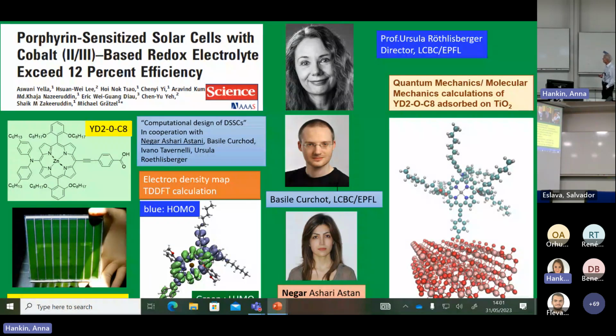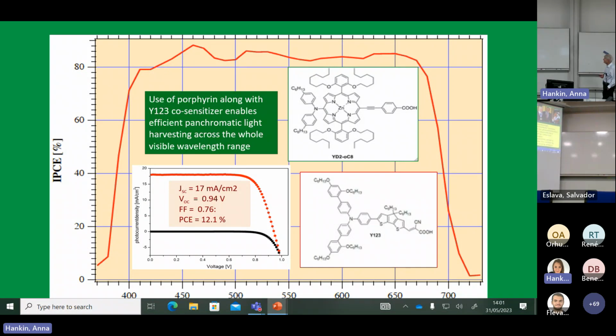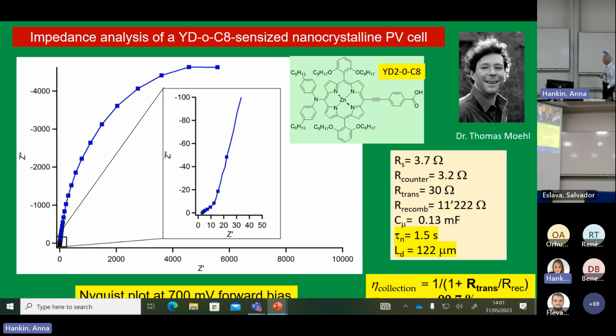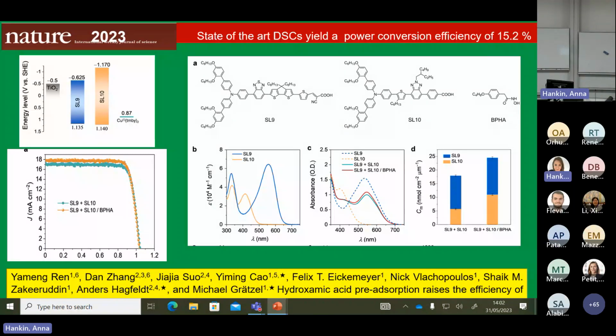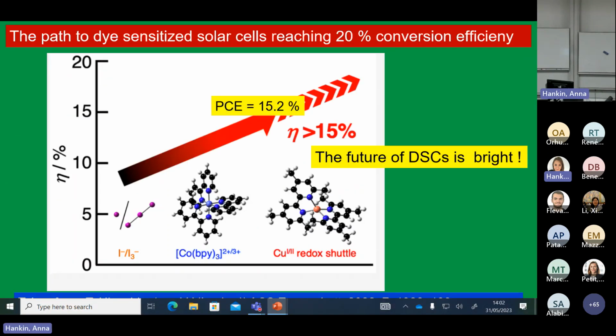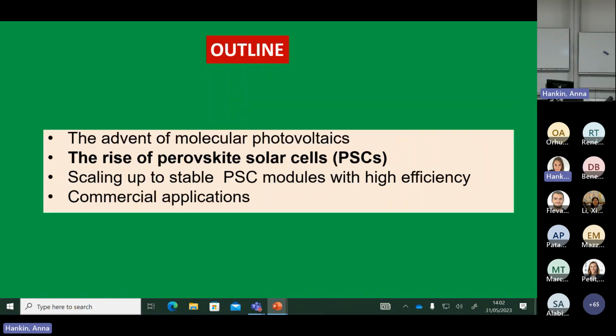So that makes very long lifetimes, and you get very high IPCE, very high EQE values, close to 90%. And now when you look at the lifetime of the charges, they're over 1 second, and the diffusion length is 120 micrometers. It's like a silicon photovoltaic. However, you achieve that with a much smaller dye quantity and much cheaper materials. And so these are today's mesoscopic systems. We have gone up mainly by doing a lot of basic research to understand what's going on in these assemblies, and by working on the redox couple and the solid state system. And so research is continuing in this field.